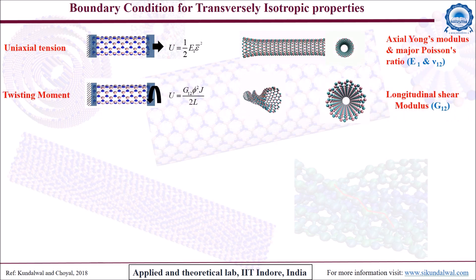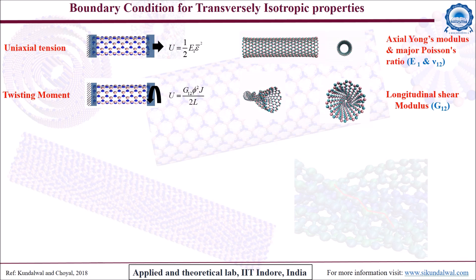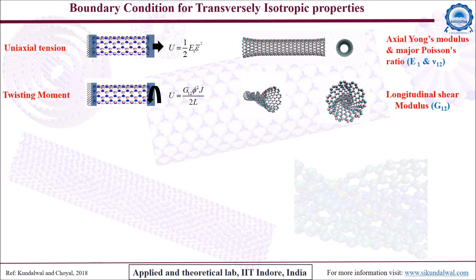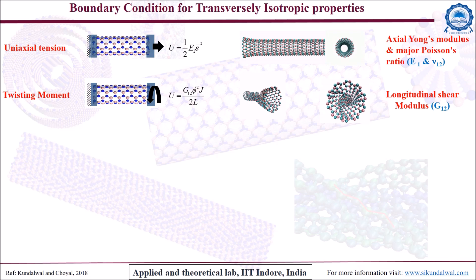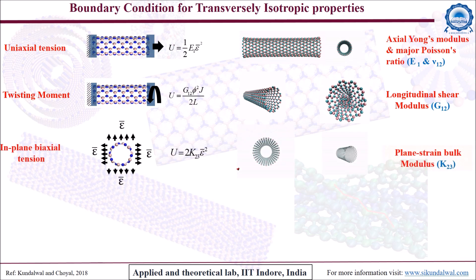In case of twisting moment, the atoms at the bottom end were fixed and at the top end a constant rotation was applied. All atoms were constrained radially in the transverse plane to maintain them on the cylindrical surface of the BNNT. The strain-energy density of a BNNT can be expressed by a given relation.